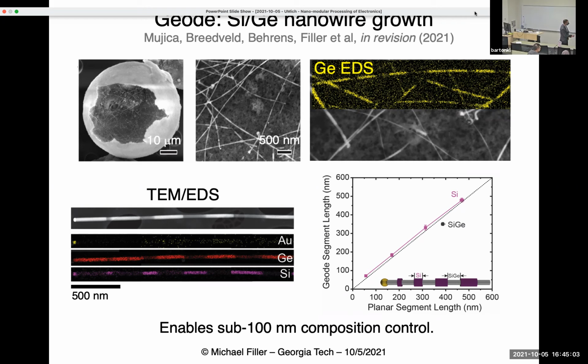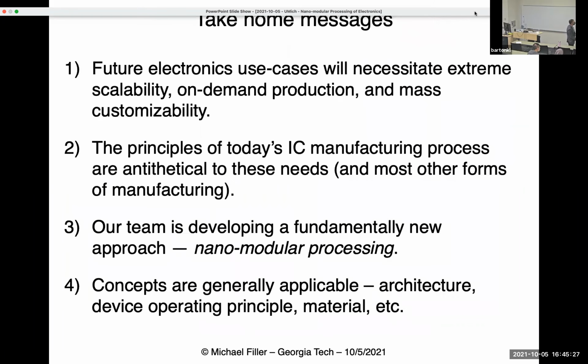And then if you look at the TEM, when we do harvest some wires, you can see very clearly the modulation between silicon and germanium that we can get inside of the capsules. And we can go all the way down to 75 nanometers. So we have very good nanoscale control, even inside this capsule. The transport of precursors is very good through the wall of the capsule. And that's kind of where we are. So we worked on this for a couple of years, and obviously we've made some nice progress. We have plenty more things to do.